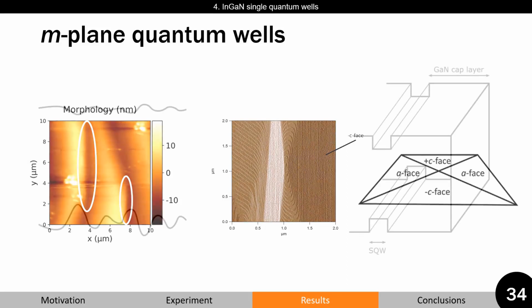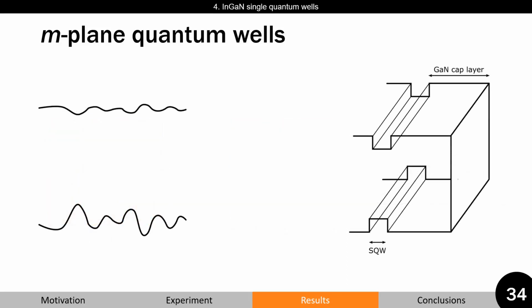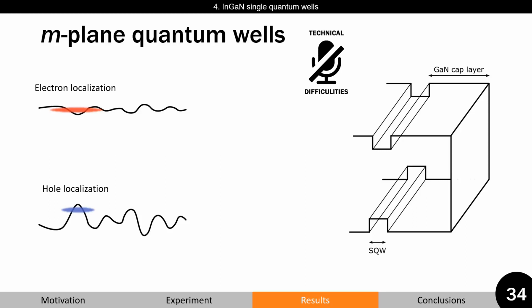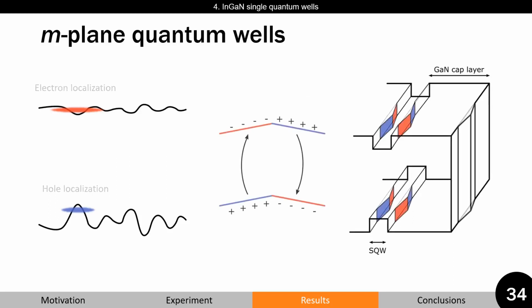Then, to understand the origin of prolonged times, it is useful to invoke the notion of carrier localization. In nitrides, holes are known to be strongly localized, well-defined in space, while electrons are not. In the case of flat quantum wells, these pyramid-like hillocks are formed because the surface charge accumulates next to the interface, and a small electric field is introduced into our quantum well structure. Thus, an in-plane component is introduced, which can then push our weakly localized electrons in space, hence reducing the spatial overlap between electrons and holes, prolonging the radiative lifetime.